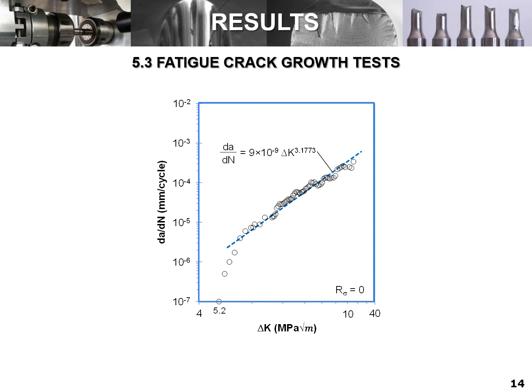Overall, the scatter is relatively low, either at the threshold area or at the Paris regime. The threshold value is equal to 5.2 megapascals root meter. Thus, based on the previous values of the stress intensity factor range threshold and the fatigue limit stress range, we can determine the material characteristic size, A0.